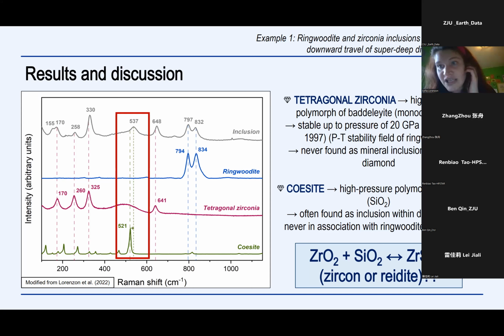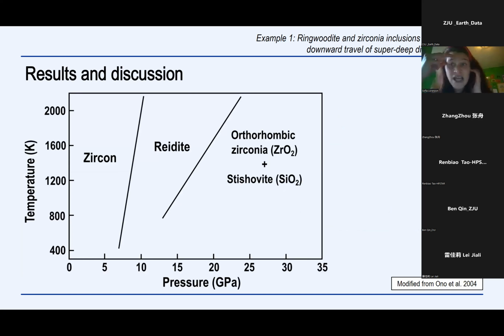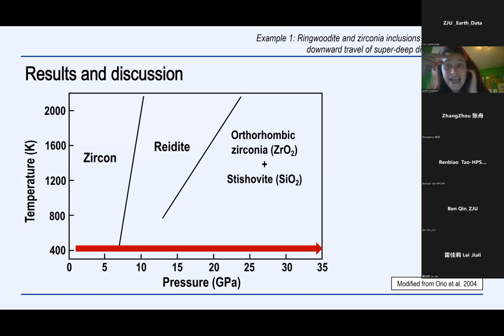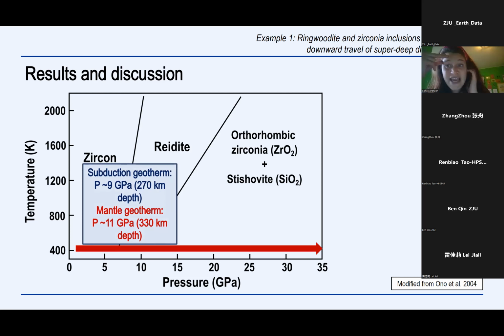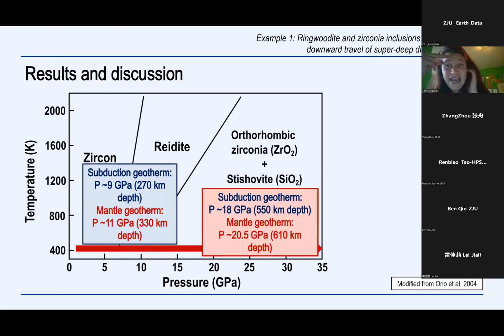So, to understand this better, we analyze the pressure and temperature stability graph of zircon. And we observe that if we increase the pressure, zircon will transform into reidite at a pressure of about 9 to 11 GPa, which corresponds to 270 or 330 kilometers depth if we follow the subduction or the mantle geotherm. But more important, if we increase the pressure more, reidite will transform into orthorhombic zirconia plus stishovite at about 18 GPa and 20.5 GPa, which correspond to a depth of about 550